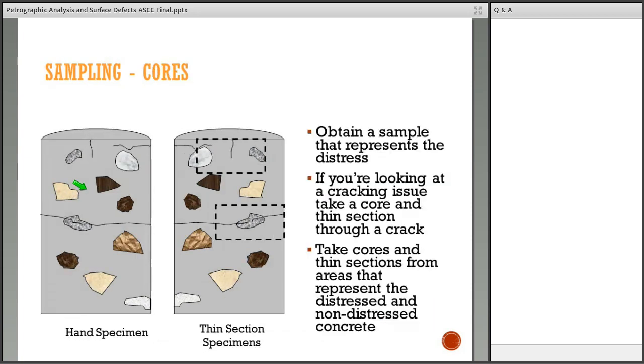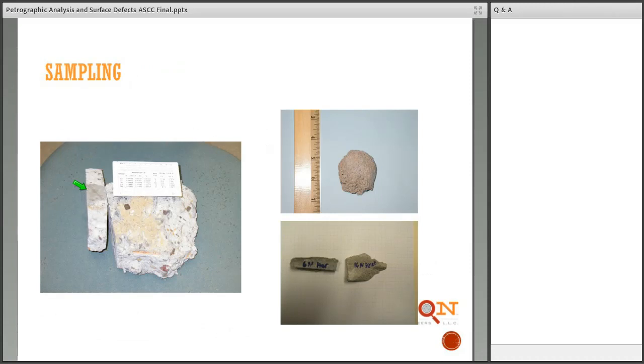Especially if you've got cracks and whatnot, you take thin section specimens out of areas of interest, especially where you've got cracks. So basically take cores and thin sections from areas that represent the distressed and non-distressed concrete. That's usually helpful in helping you determine possible causal factors as to why it behaved the way it did. Sampling, usually we'll get maybe a chunk and we'll cut slices out of it, thin sections out of it,